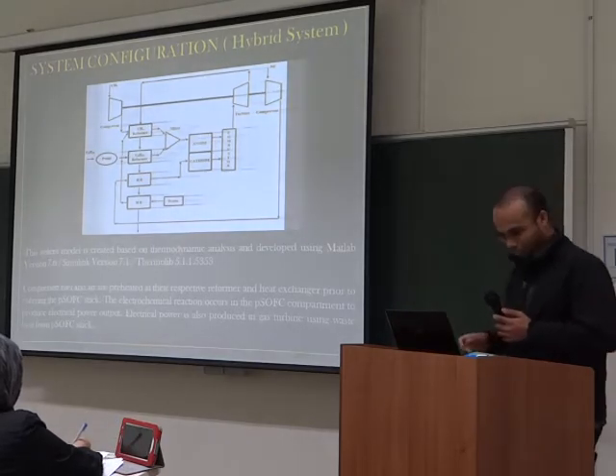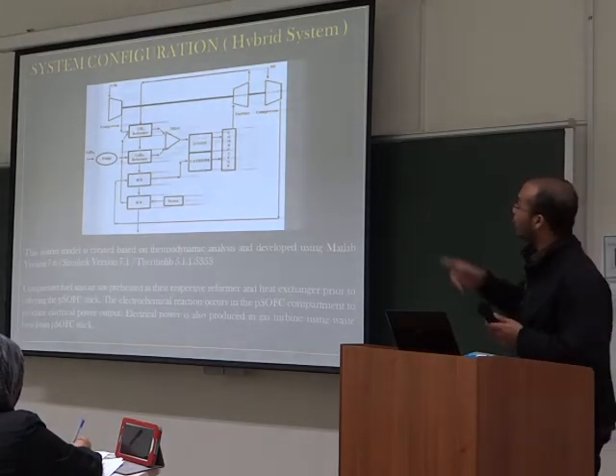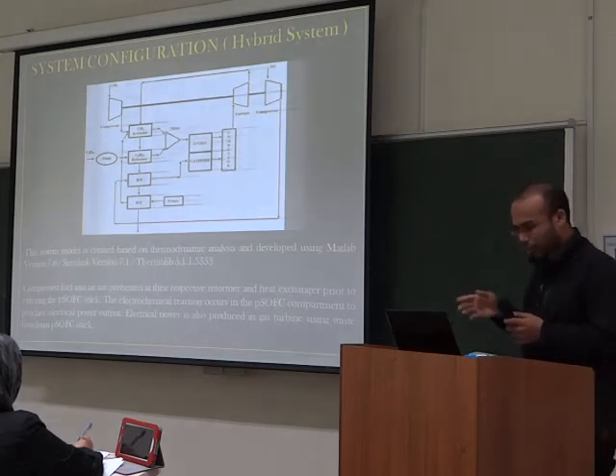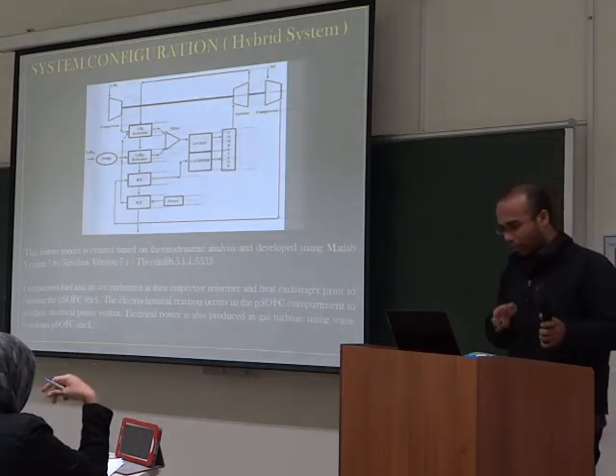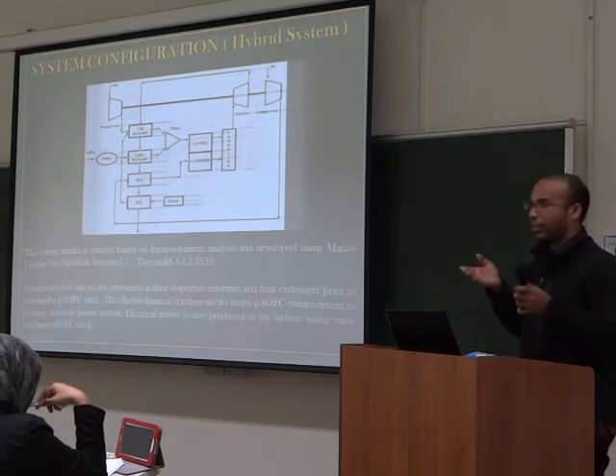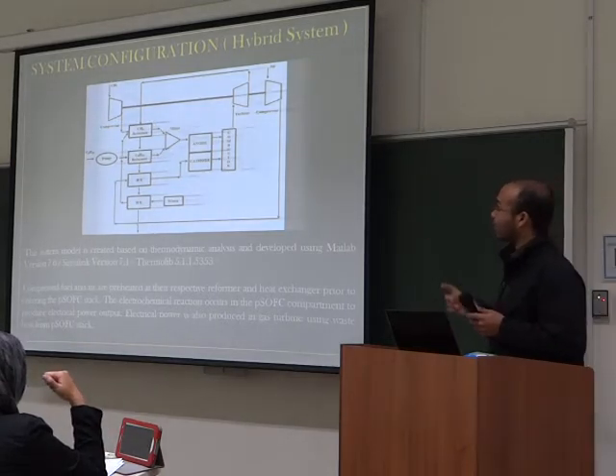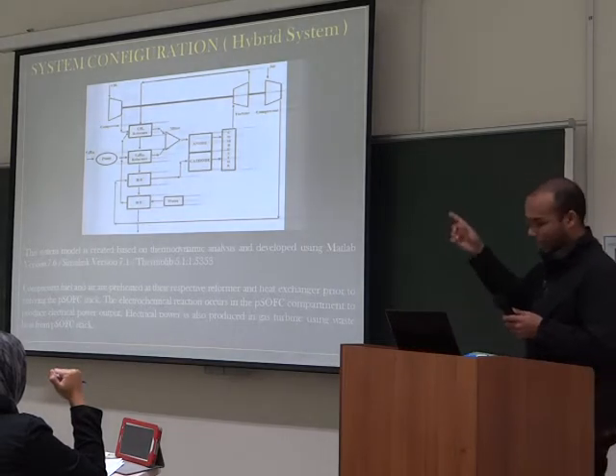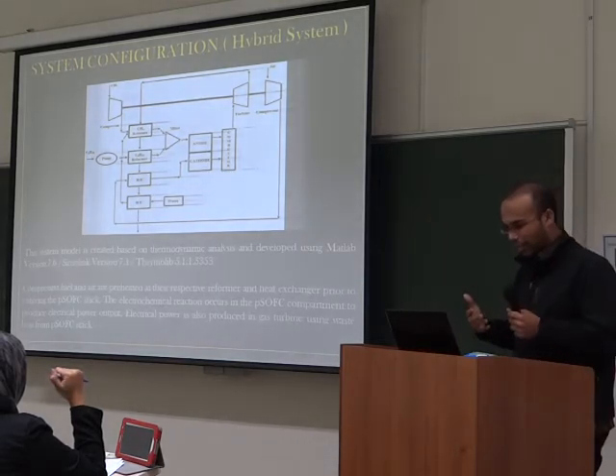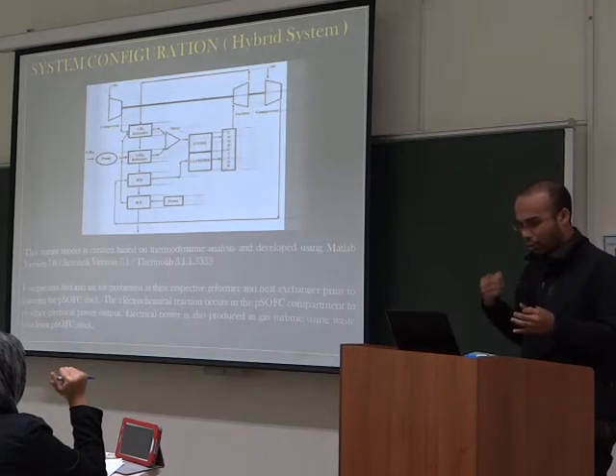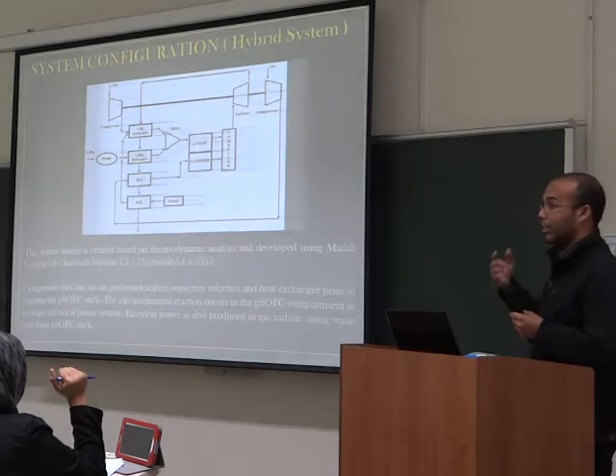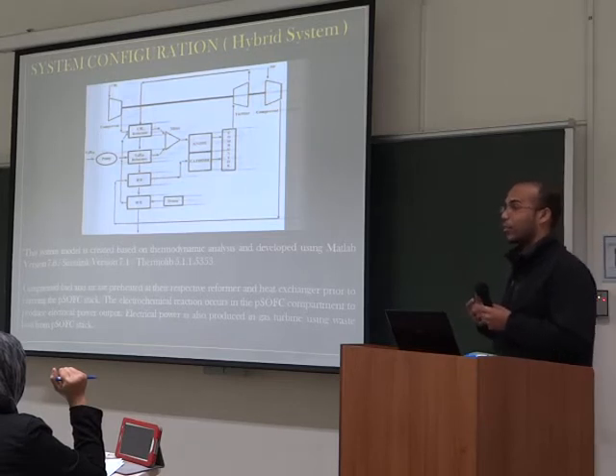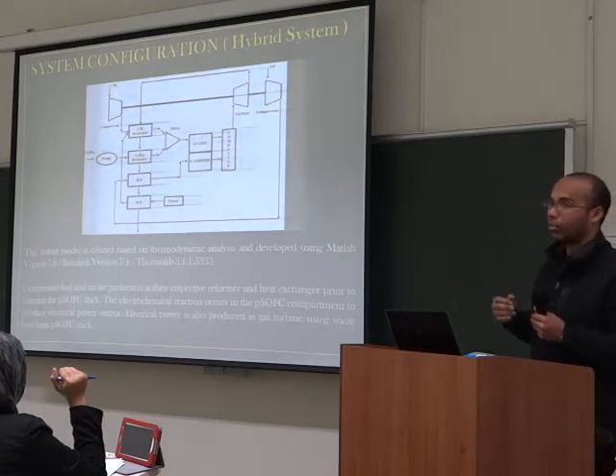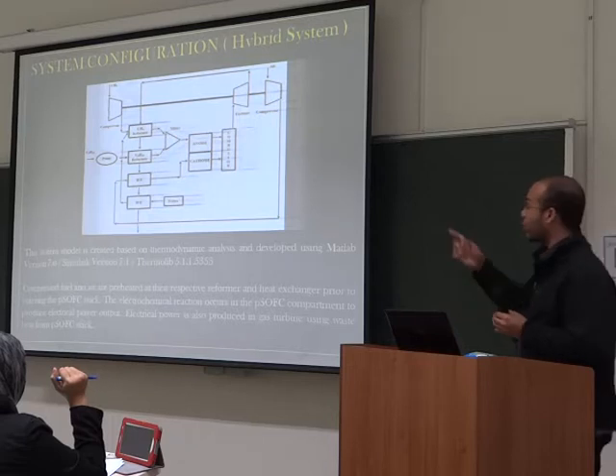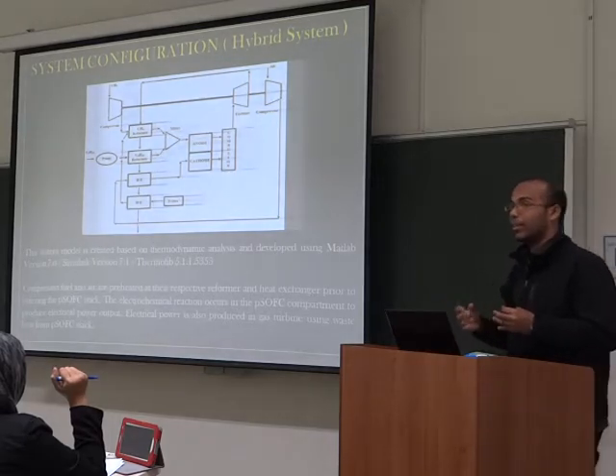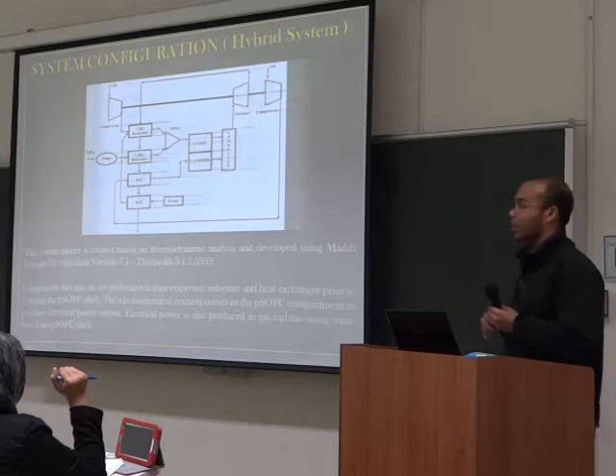hybrid system. First, compressed air and also the fuel are preheated in the catalytic reformer and also the heat exchanger to increase the temperature before entering the stack. And then in the stack, the electrochemical reaction occurs in the stack compartment to produce electric power. Because in the fuel cell, not 100% of the fuel can be converted to electricity, there may be some unreacted fuel, so we use a combustion chamber to burn it, to increase the temperature for use in the microgas turbine, to increase